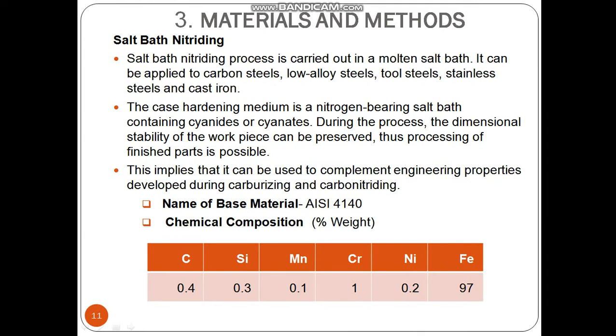Salt bath nitriding. The salt bath nitriding process is carried out in a molten salt bath. It can be applied to carbon steels, low alloy steels, tool steels, stainless steels and cast iron. The case hardening medium is a nitrogen bearing salt bath containing cyanides. During the process, the dimensional stability of the workpiece can be preserved. Thus, processing of finished parts is possible. This implies that it can be used to complement engineering properties developed during carburizing and carbonitriding.